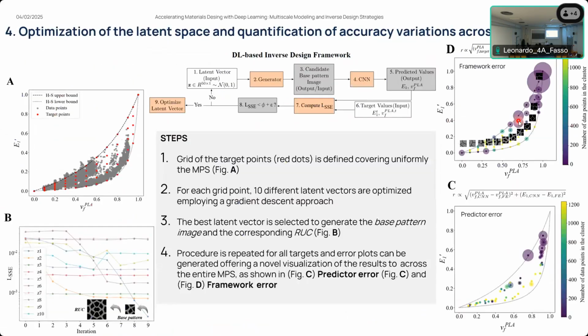Next, as you can see, we obtain large errors for the points that are in the region where there is almost no training data. And for the regions where there is a lot of data, we can see very small errors, both for the predictor module, so the forward module, and also for the inverse module, which is the entire framework. So this is why we have 2 error plots here. We obtain very big errors here, which is expected.